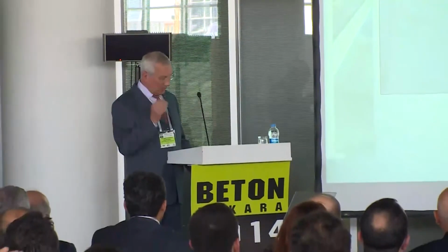And a joint according to the red line would have been better. In this case, the transversal joint is blocked and a crack appears along the joint. Why? Because it is necessary to avoid placing dowels in the two perpendicular joints. And the designer must locate the joints in such a way that any sharp corners are avoided.